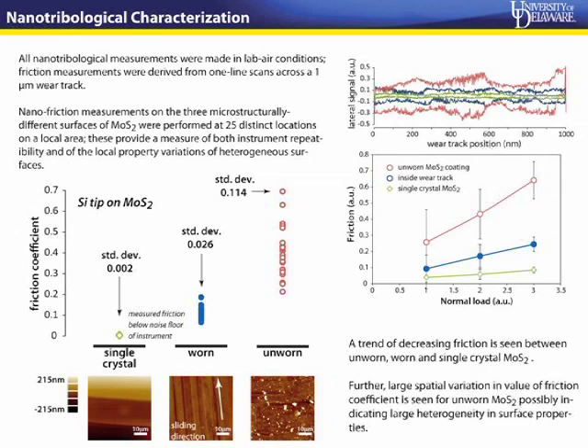One of the key observations of this experiment was that you get fairly high variability on the as-sputtered unworn MoS2 coating, whereas friction is lower, presumably again because of tribofilms, and you get much lower standard deviation within the wear tracks. And of course, single crystal is much smaller than these.